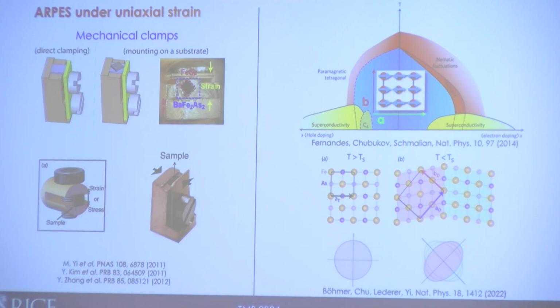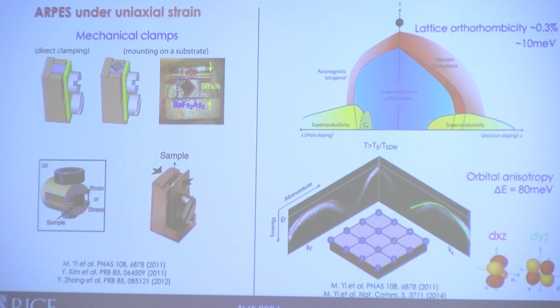uniaxial strain devices. And this is really driven by Ian Fisher's group's work, where they developed this clamping device. Basically, you can glue your sample, press it along one direction, and then this will help the sample to prefer one orientation over the other, and then get a largely detwinned crystal, in which case you can measure all the intrinsic properties that you want. So we adapted this for photoemission. This is the initial kind where you just clamp it, and then these are independent developments by other groups, from Chang-Yang Kim's group here, developed by Yongquan Kim, and also this is the device from Donglai Feng's group back in the day. And using this, we were able to look at the intrinsic property of the nematic order.